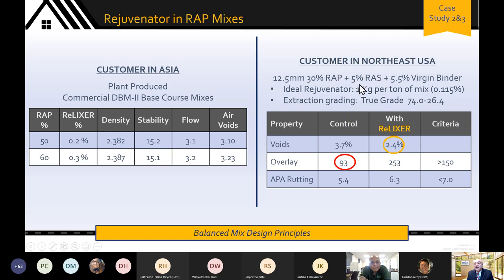So it's about a 40% ABR to which 5.5% binder has been added. Case A, no rejuvenator. Case B, with rejuvenator. And we're measuring overlay, Texas overlay, interlaminar shear fatigue kind of a test to assess the damage tolerance properties, and APA rutting to look at the rutting properties. You can see the kind of balance we're trying to make here. Clearly, you're trying to improve the damage tolerance and take as minimal a hit as you can on the rutting so as to be able to meet the criteria here.